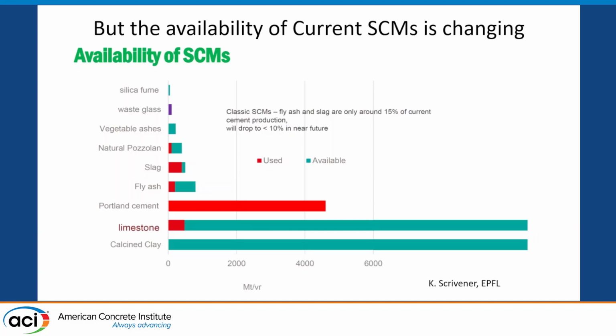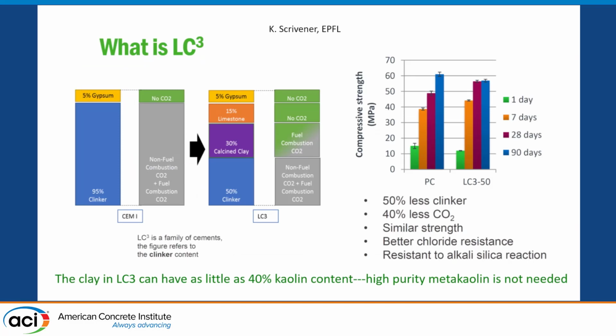So what's available for these people if we're not going to have more coal-burning power plants, and the blast furnaces are being converted into electric arc furnaces, so the amount of that blast furnace slag will reduce in availability over time. And you can do all these things. People talk, I'll talk about these other standards, they're relatively small proportions. So what's available is raw limestone and clay that can be calcined. It doesn't have to be high-quality clay, just can be calcined and blended together, and you can replace, as Mary showed, 50% of the cement, and this is the same graphic she showed, 50% less clinker, about 40% less CO2, just using a different pozzolan.